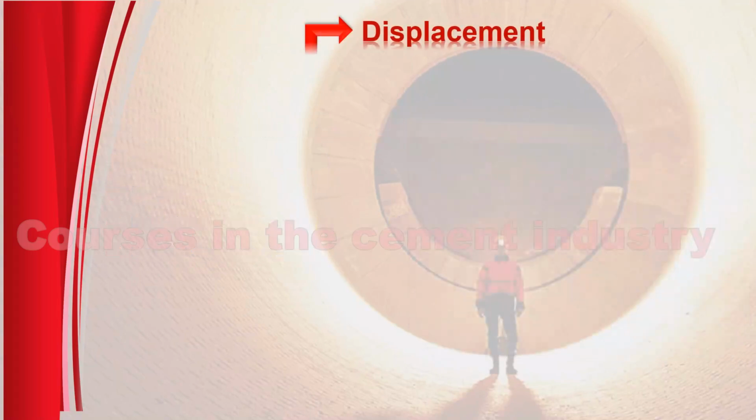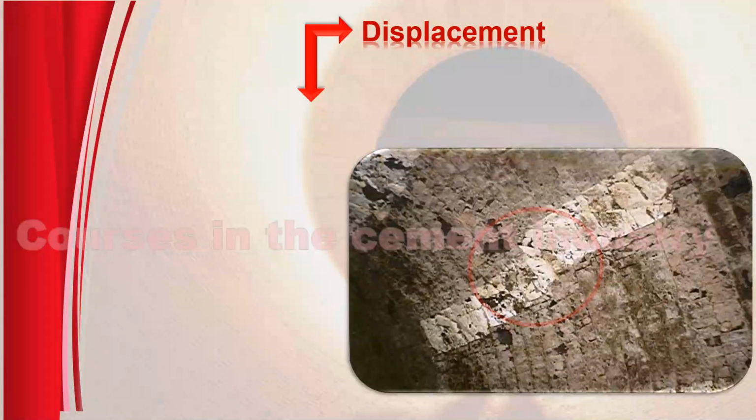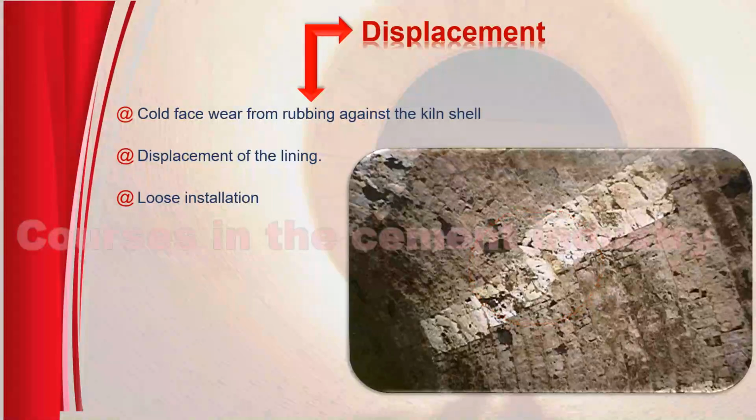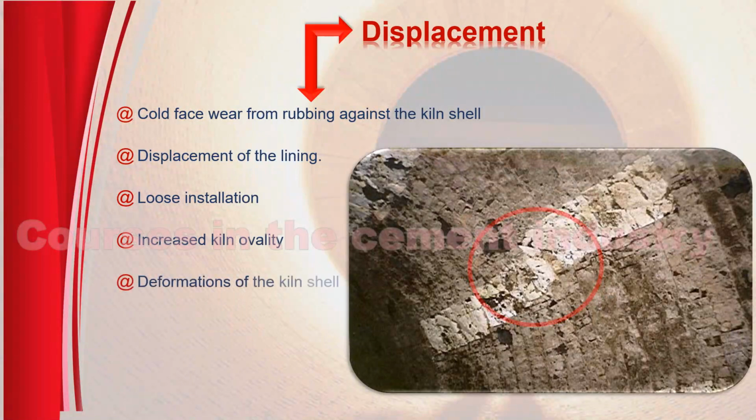Displacement. The main reasons for this are: 1. Cold face wear from rubbing against the kiln shell. 2. Displacement of the lining. 3. Loose installation. 4. Increased kiln ovality. 5. Deformations of the kiln shell.